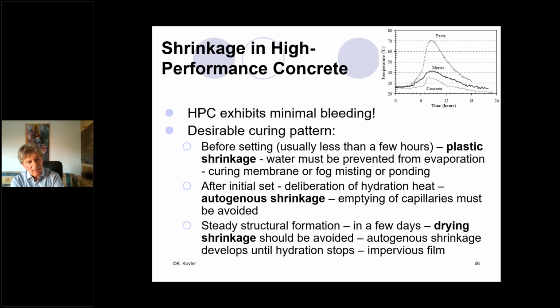So in this sense, bleeding can sometimes be very positive, in spite of the fact that most builders, most of our researchers and engineers consider bleeding as something hazardous. But for example, for concrete pavements, when we have a high surface of evaporation, it can be nicely utilized. So plastic shrinkage happens in very, very early time. Then we have, after initial set, autogenous shrinkage, when capillaries are emptying, and this should be avoided, of course. And when we have steady structural formation, in a few days, we have the start of drying shrinkage. Of course, we need to avoid it, because autogenous shrinkage develops until hydration stops and we have an impervious film. So in principle, we need to take care of both autogenous and drying shrinkage when the age of concrete exceeds hours and days.